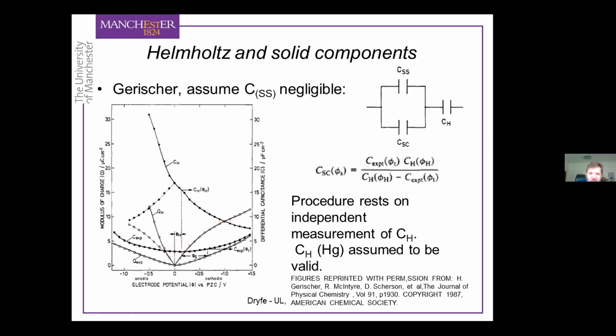And then he says, well, I know my total experimental capacitance. The charge stored in the Helmholtz layer should be the same as the charge stored in the solid. So by equating these two charges, I can then work out what the potential drop in the Helmholtz layer is, and therefore what the potential drop in the solid would be. And therefore, once I know those things, I can put the capacitances together and extract the capacitance of the space charge region, the capacitance of the graphite. And that works reasonably well, that procedure.